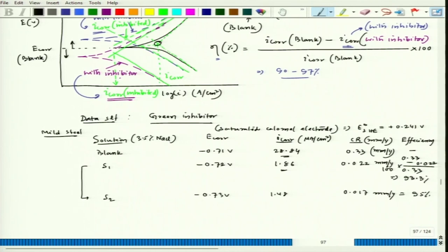So that way we could see how to calculate efficiency and how to see the effect of dose. But remember, the dose should be as minimal as possible, because inhibitors cannot be added to a great extent because it will influence other aspects. For example, if it is a cooling water system, the inhibitor can actually influence heat transfer efficiency. So we should add as minimum as possible, but at the same time, we should also look at this inhibition efficiency, that the effect on corrosion rate should reduce drastically.